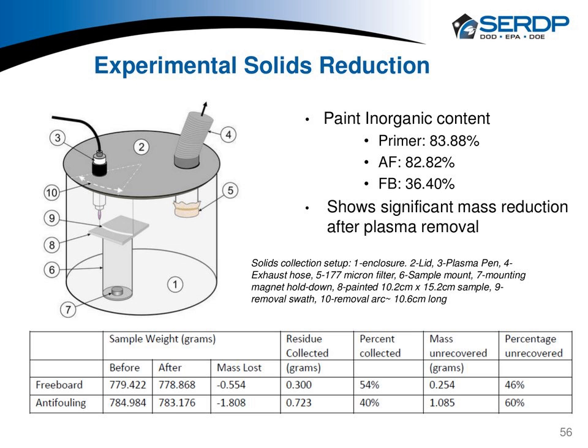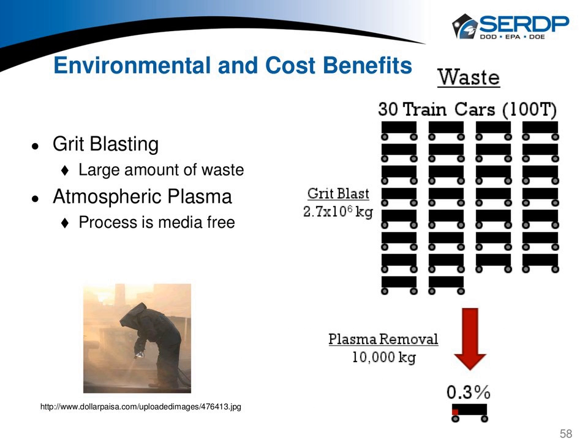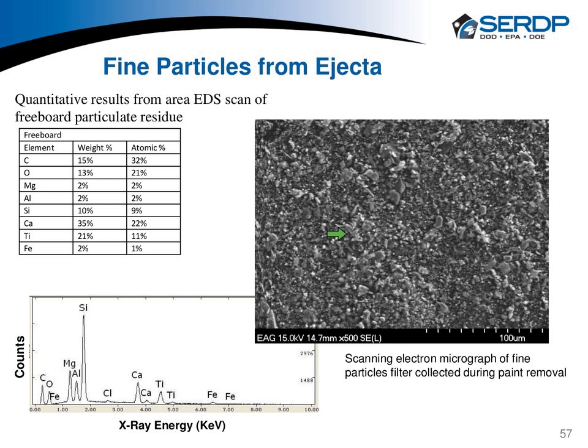So I'm going to skip to this slide and get right to it. This is a pretty good summary. If one is using grit blasting to remove paint, this is the volume of material that you're going to have before and or after the painting. With a plasma, we don't need any of that grit, and it's a very small fraction of material that needs to be recovered. So let me go back to this real quickly. This is SEM of some of those particles. The bottom line is that after plasma treatment, the waste ejecta is primarily the inorganic fillers that were in the paint to begin with, and some of the paint residue, depending on how quickly the plasma was rastered over the surface, etc.